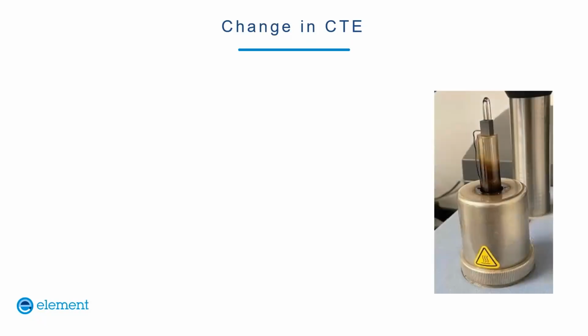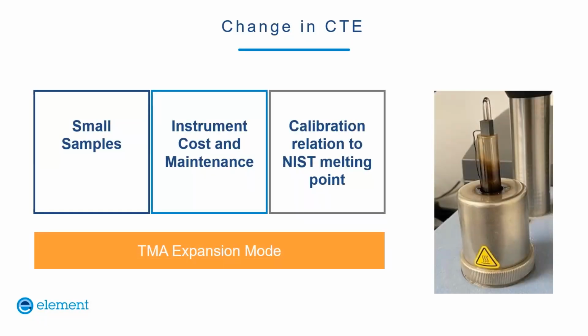We can also measure the change in CTE, and we do that with a TMA, or thermomechanical analysis instrument. The instrument uses a small sample on a quartz stage. Here the sample again is black. This is a quartz stage. This is a quartz rod that sits on top of the sample. We use quartz because it has a very low coefficient of thermal expansion itself, and therefore the baseline of the instrument is almost trivial. It's not quite, we correct for it, but it's very low. And then this wire is actually the thermocouple wire that measures the temperature of the specimen. And then a furnace fits around this entire assembly, and again, it heats up.